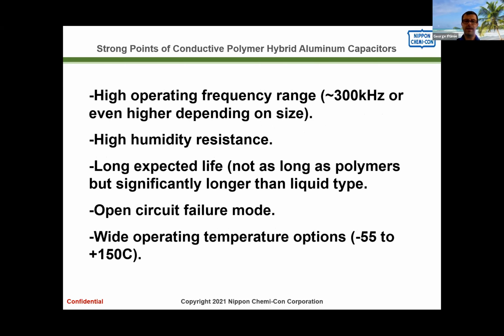They will almost invariably, I mean, "always" is a dangerous word to use again. Assuming that it's not severely overstressed, the failure mode will be open circuit. So it will dry out essentially like an electrolytic capacitor versus failing as a short circuit like a polymer, which is an expected failure mode. And they have a very wide operating temperature, -55 to +150 degrees C.